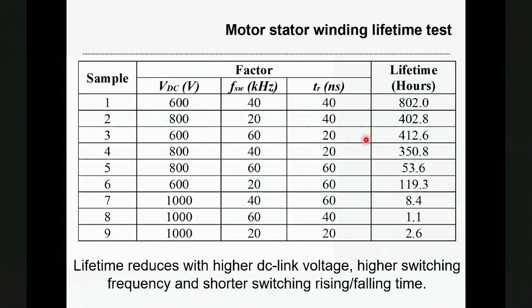We have also tested several motorettes. That is a motor stator winding with a core. And there are 9 samples. And they are driven by silicon carbide inverters under 3 different types of DC link voltages. That is 600 volts, 800 volts, and 1000 volts. 3 different switching frequencies, 20 kilohertz, 40 kilohertz, and 60 kilohertz, and also different driving times. And basically, high DC link voltage and high switching frequency will clearly reduce the lifetime of the motorettes or the motor stator windings.